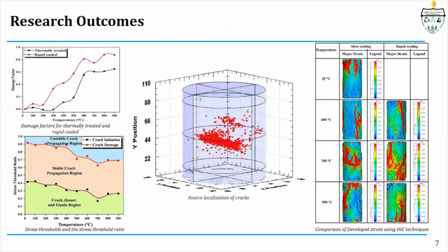The various structural damages in rocks in the form of cracks are due to induced thermal stress. The differential thermal expansion of different minerals along different crystallographic axes give rise to various levels of thermal stress in the rocks that result in structural damage. Also, these structural damages in rocks are due to various chemical reactions and phase changes of the minerals because of increasing temperatures. We have quantified the damage factor of the thermally treated and rapid cool specimen to measure the extent of structural damage in the structures of the rock.